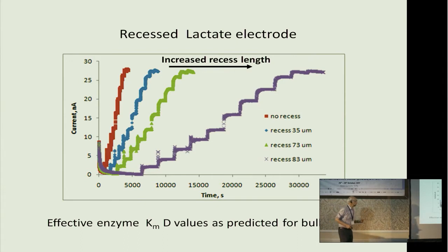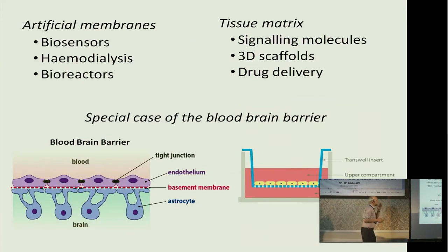Generally, interestingly, the diffusion coefficients through that recess are pretty much as they are in bulk water, bar one type of molecule, anionic molecules. And the weird thing is that my device and its recess has got no real charge on the inside. So what is going on with retardation and ionic molecules? So this is a model system to try and take a look at. So we studied that, but I wanted to then adapt it to something that has simply shocked me after 30, 40 years of research.